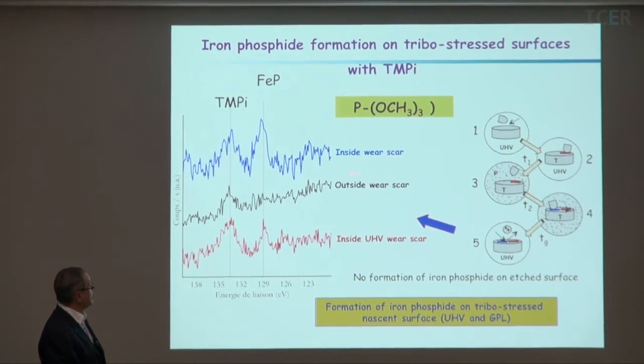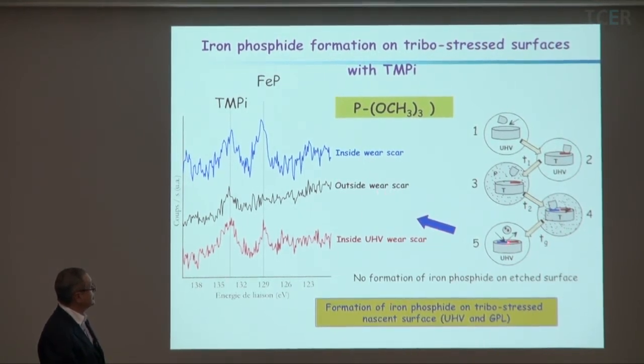This is outside the wear scar here. You can see that there is only this peak in the XPS spectrum. And this is the molecule which is adsorbed on the surface. The molecule is adsorbed at the surface anywhere, in any place. But inside the wear scar, you see the molecule which is adsorbed, but there is a new peak, a new chemical species here. And this chemical species is iron phosphide, FeP, different from the phosphite. So this is a new compound formed by the tribochemical reaction.